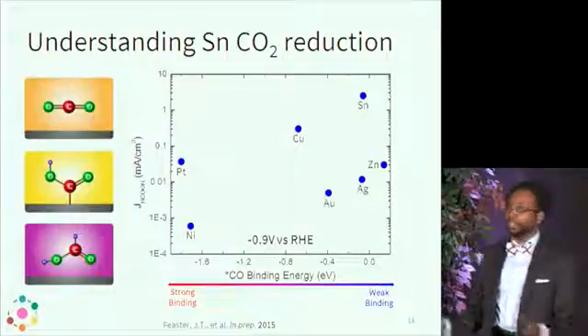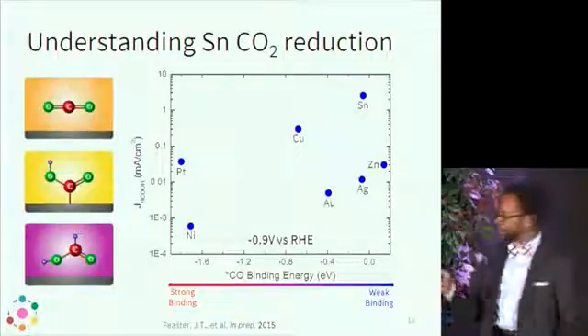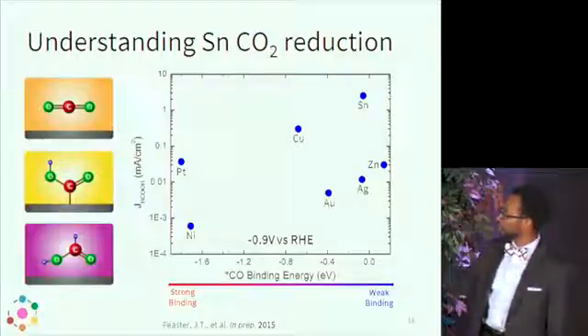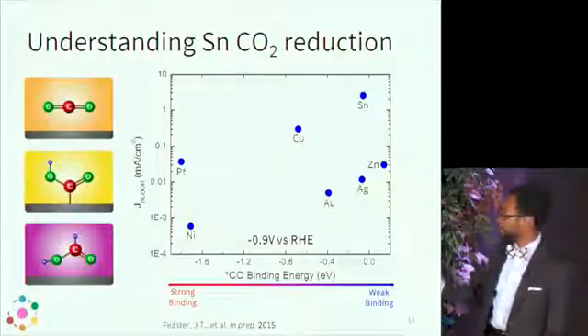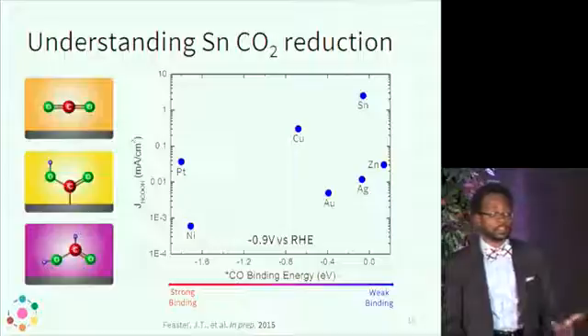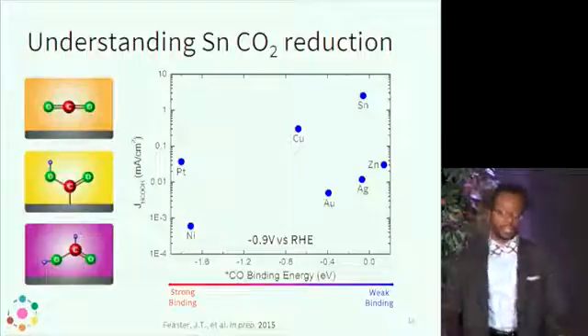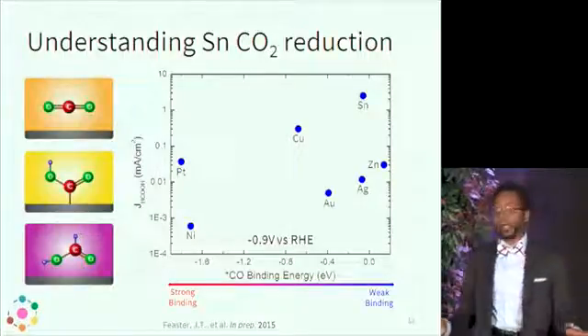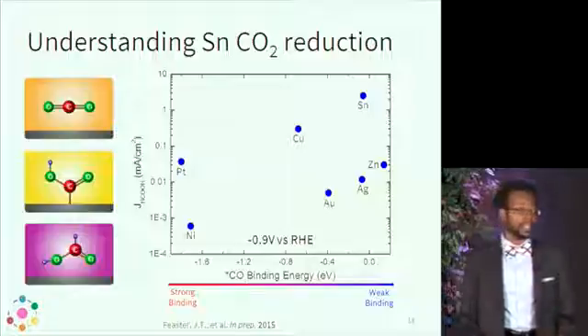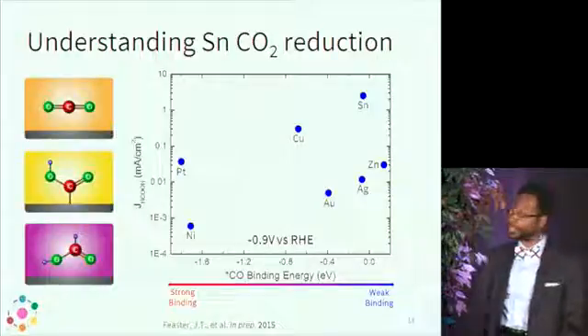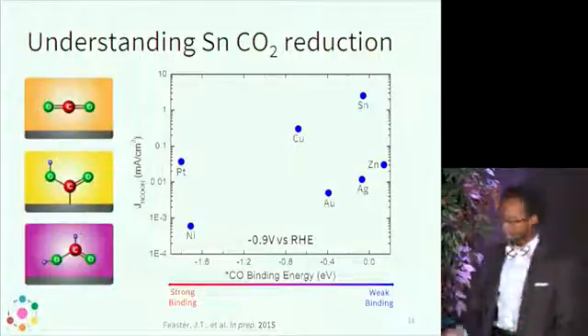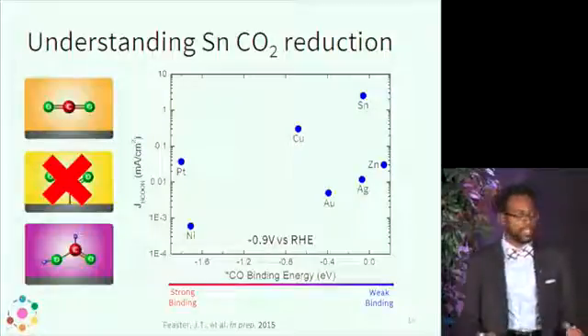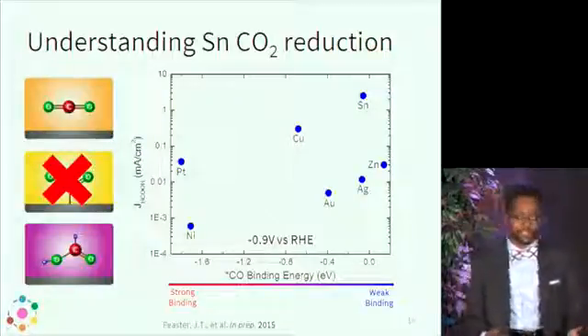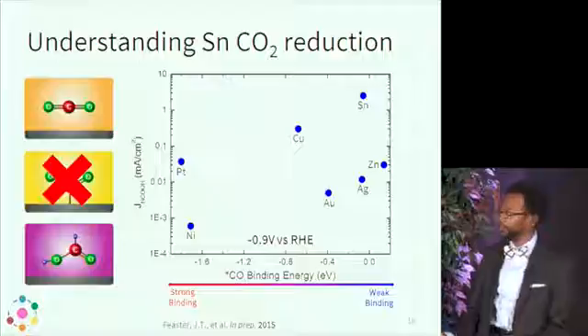We're not able to see any volcano-type behavior, and really what jumps out to you is if you look at tin in the upper right region of that plot versus silver, which has a very similar binding energy for that intermediate, it seems like there's a complete orders of magnitude difference in the amount of formic acid that tin is able to make versus silver. So this is something that kind of gave us a hint that maybe this carboxylic acid intermediate on the surface isn't the best metric to use to try to describe CO2 reduction.